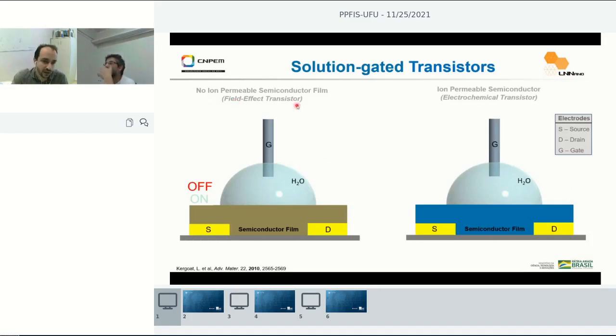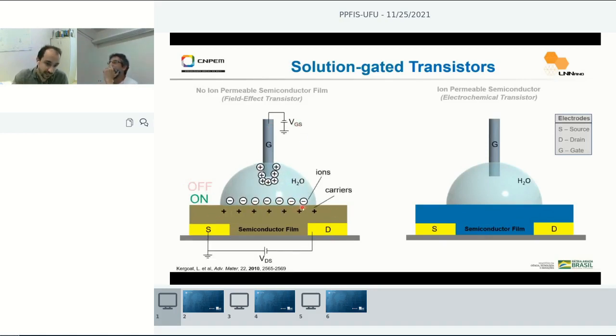The first possibility I call the field effect solution-gated transistor, where the semiconductor film is non-permeable to solution ions. This means that you have a substrate, the pair of source and drain electrodes, your semiconductor film, you place a drop of water or salt electrolyte on top, and you immerse the gate electrode. For example, you can use a metal wire here. Then by applying a given voltage to this gate electrode, since the semiconductor is non-permeable to ions, you will form the electrical double layer at the gate interface and an electrical double layer at the semiconductor interface. These ions will induce carriers in the semiconductor film. In this case, you switch your transistor from on to off, from off to on.